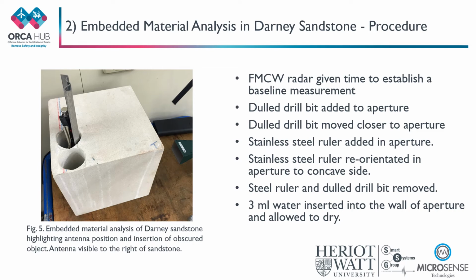The second experiment was designed to identify if the FMCW radar was sensitive to embedded rebar within Darney sandstone. An aperture was drilled into the Darney sandstone so that materials could be easily inserted to simulate different types of rebar and other scenarios. As viewed to the right of figure 5, the antenna was positioned 10 cm from the target interface on the Darney sandstone.